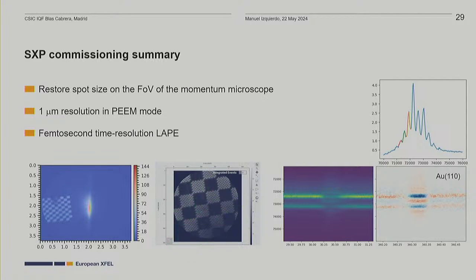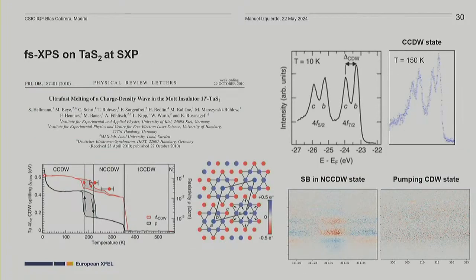And then the femtosecond dynamics. So basically what we do is to measure what we call laser assisted photoemission, so LAPE. And you see here the LAPE experiment we did on gold 110. That is going to be one of our references. And then you see here these are the two core levels, and these are the orders of LAPE that you can excite, that depend on how clean your surface is and how powerful the laser is as well. So in April this year, we did the first experiment.